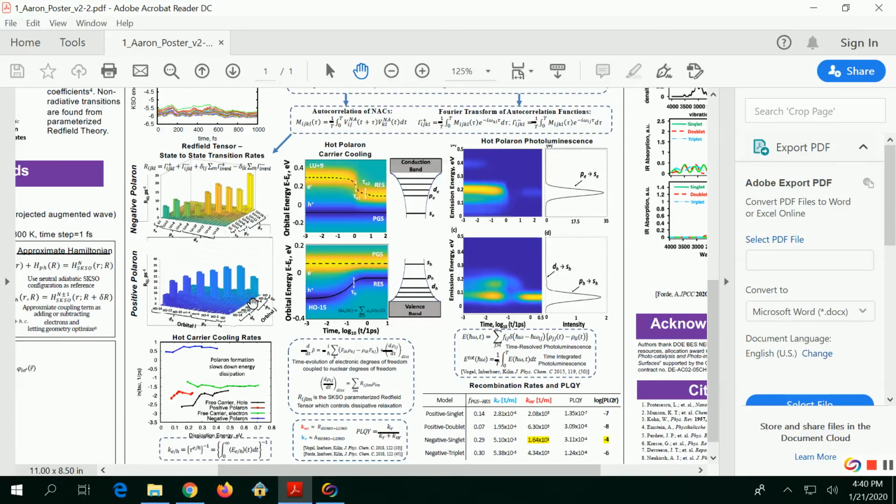You can characterize the cooling rates in these systems if you assume that they should decay as a single exponential. If you plot the dissipation energy, or the excess energy that you give to begin with, versus the log of time, it should be roughly linear.